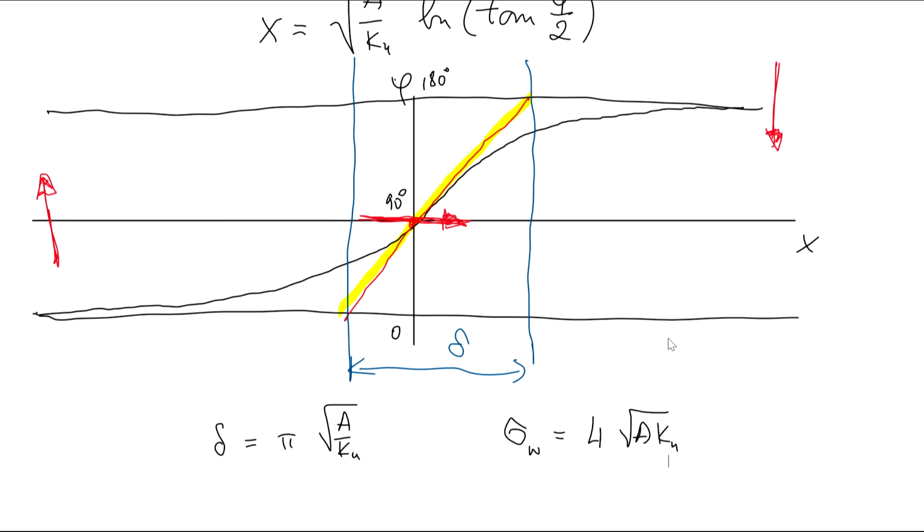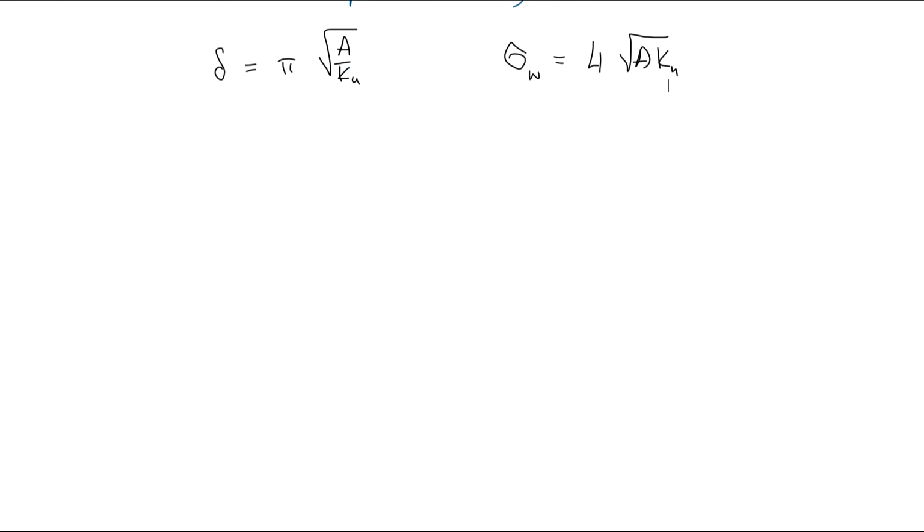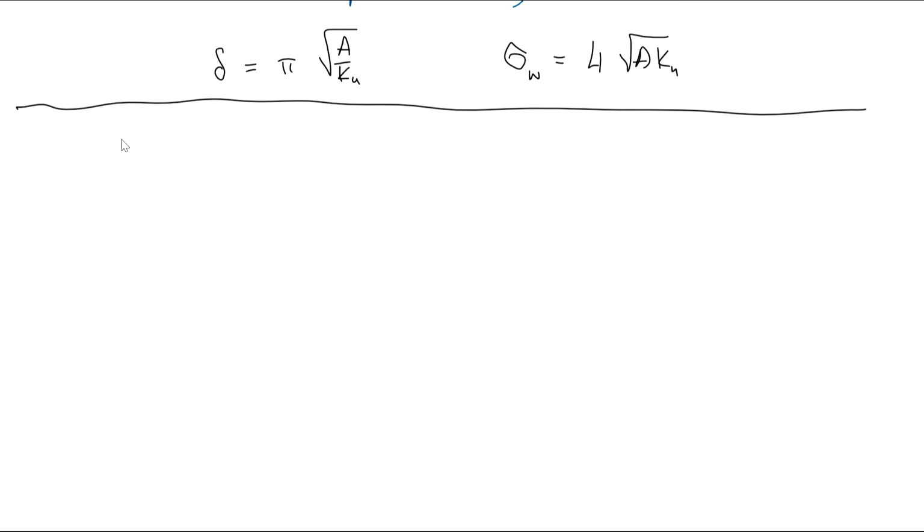So if you take iron, I could do an example of iron, but before we do so, iron is actually a BCC lattice. So for iron, it is not uniaxial anisotropy. For iron, it is cubic. So what we have to do is take cubic anisotropy, substitute it into the integral for cubic anisotropy type, and calculate.